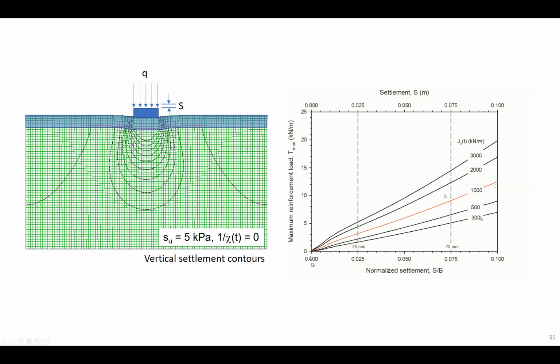And you can see that as the stiffness increases, the load in the reinforcement is increasing as well. In fact, if you look at these numbers, you can see that there's about a threefold increase in the maximum tensile load in the reinforcement as we go through one order of magnitude, from 300 to 3,000 kilonewtons per meter. So the stiffness does play a role in the loads and obviously the strains that are going to be developed in the reinforcement.